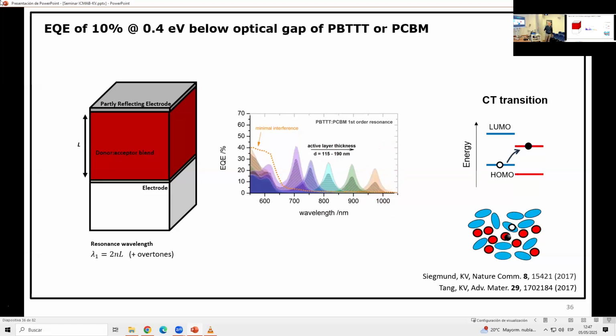So now, without needing any chemist, you can still make something which absorbs at a wavelength which you couldn't do with any of the 2 materials, but when you blend them and you have the CT absorption, you can pump this up just by changing thickness. So you feel almost like a chemist. That felt good at the time.